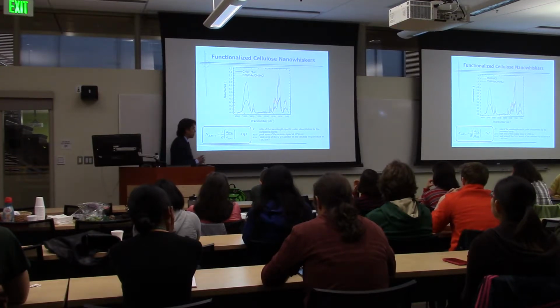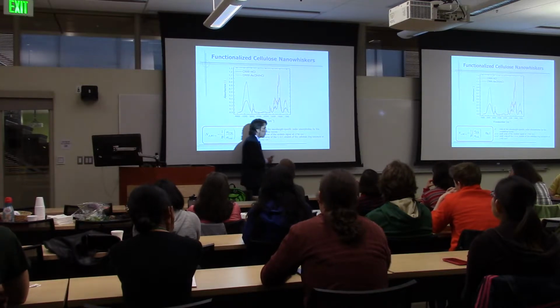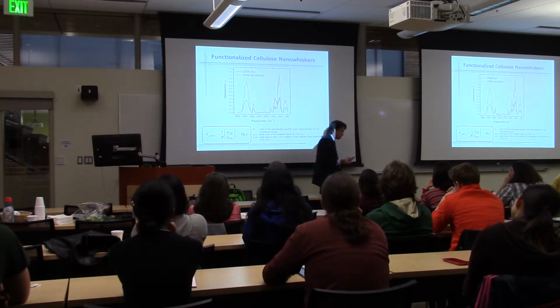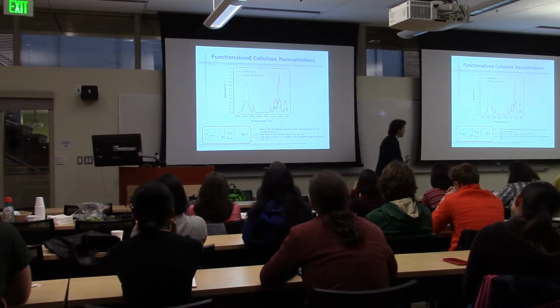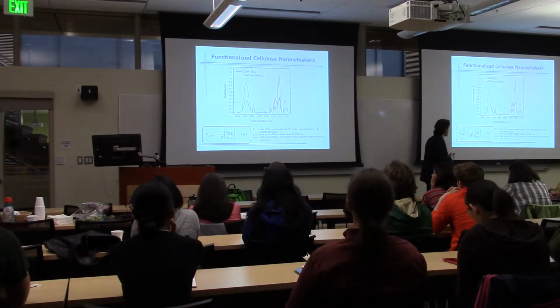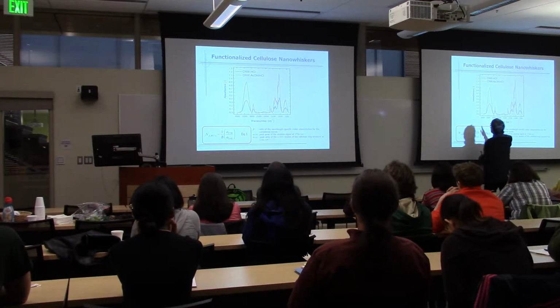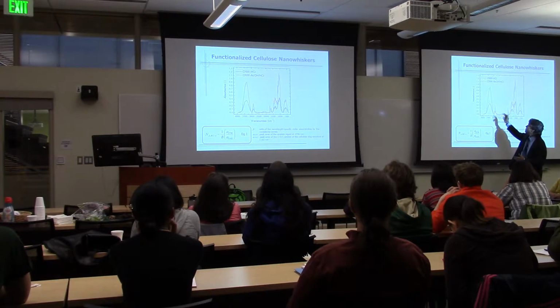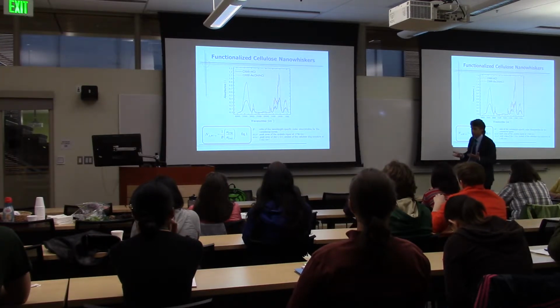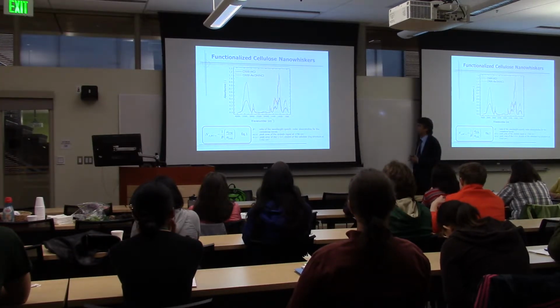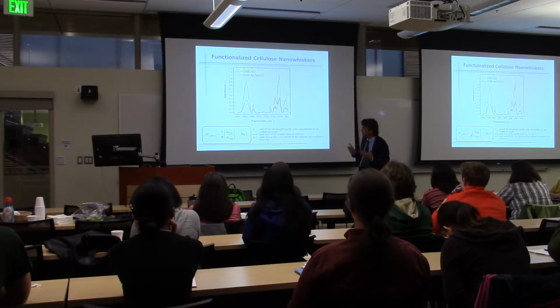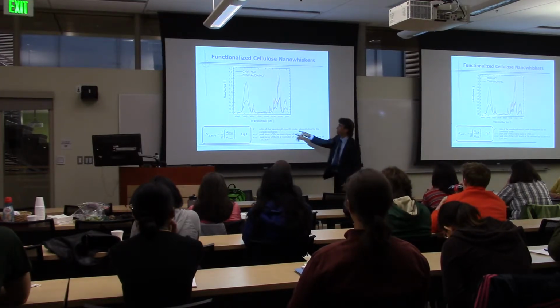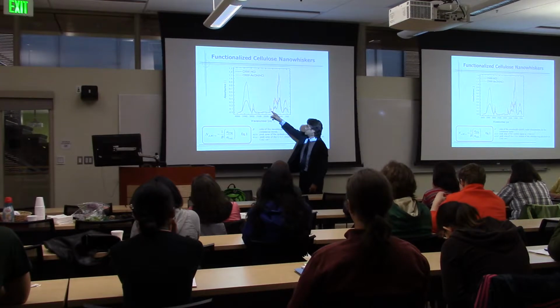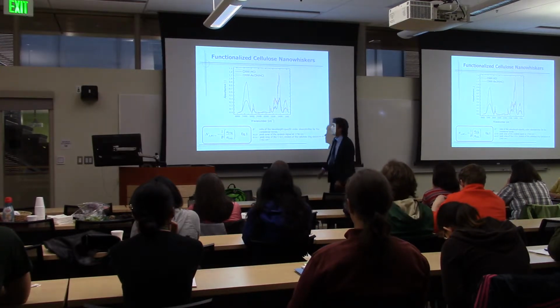Again, I like to be as quantitative as possible. And what we're trying to do now is to control the surface chemistry. And we need to quantify that in some type of a way. And what I'm showing here is a comparison between cellulosic nanowhiskers made with just hydrochloric acid and cellulosic nanowhiskers made in the presence of hydrochloric acid and acetic acid. And you can see this difference here in the FTIR spectra down here, and that's the acetate group.